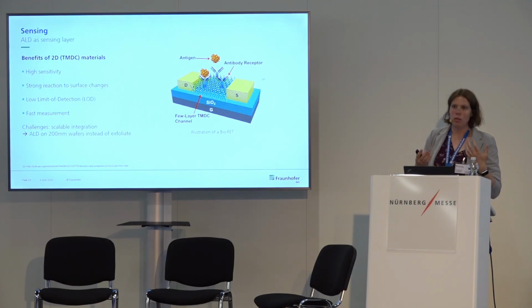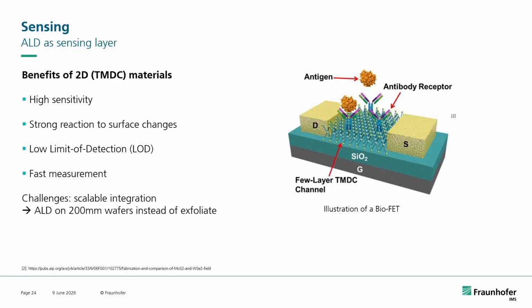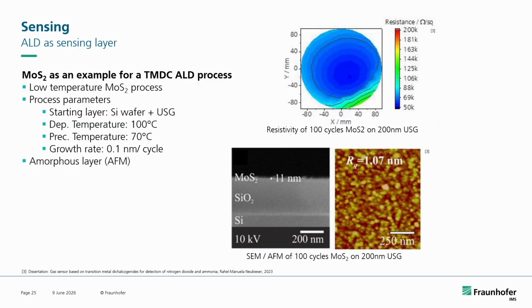So most other 2D materials at the moment are exfoliated on the wafer, so you have some kind of transfer process. So in our case, we can deposit these 2D materials on a full 8-inch wafer. So this is shown here. Here it was MoS2, and here you can see from the resistivity measurement that, okay, beside of the part on the bottom side, we have a really homogeneous deposition of these 2D materials.